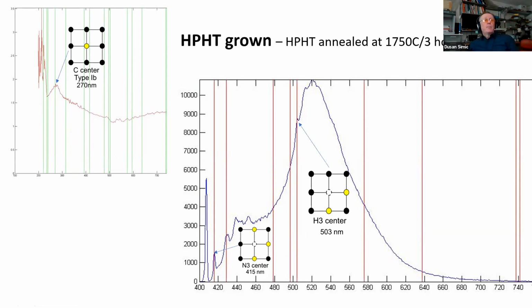aggregation was very small, because single nitrogen in the UV at 270 nanometers is still strong, but in 405 induced photoluminescence, we see the creation of 415 centers, as well as the creation of H3 centers, vacancy related centers. So it means that when people say that the presence or absence of the 415 center is enough to say that the stone is natural or treated, it is really not enough, because this treatment is nothing special. This is 1750 for 3 hours only, and still the 415 center is created.